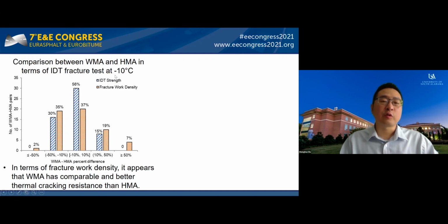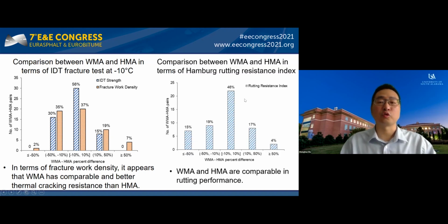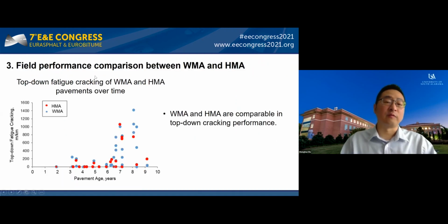So in terms of low temperature cracking resistance, we are using the IDT fracture work density comparison as well as the IDT strength. What you can see here is that in the majority, within plus or minus 10% comparison, the WMA has comparable and better thermal cracking resistance than the HMA. So the last one is about Hamburg wheel tracking testing. We are using the rutting resistance index. What we can see is that in the majority, the WMA and HMA show very comparable rutting resistance. So in terms of the field performance, for the top-down fatigue cracking, with more aging you're going to see more cracks. In comparison between the WMA and HMA in terms of the top-down fatigue cracking, they are showing very comparable performance.